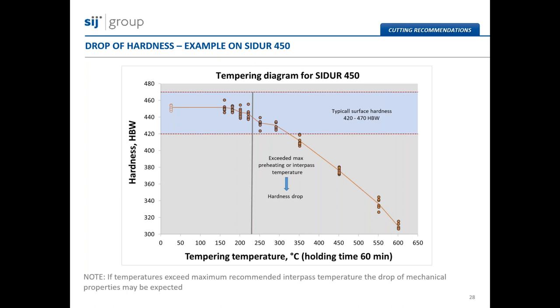For this grade, typical surface hardness in our delivery condition is between 420 to 470 Brinell. This hardness range is stable until the material temperature is in the range up to, let's say, 225 degrees C. If the temperature is higher, the hardness drop appears. And if we are doing preheating in the range of, let's say, 400 degrees C, the hardness of the steel drops to only 400 Brinell. So what does it mean? It means that we do not have the 450 grade anymore after the cutting process.